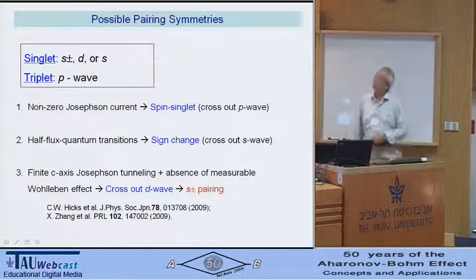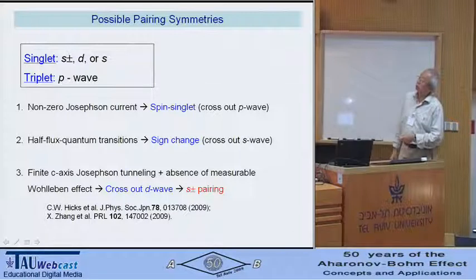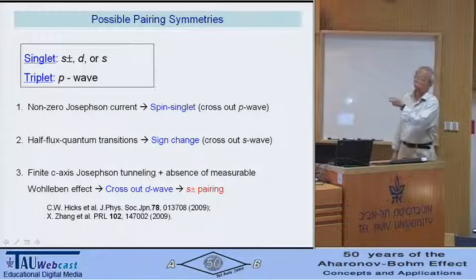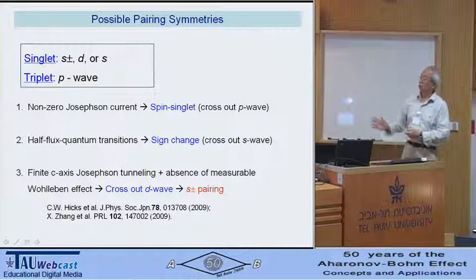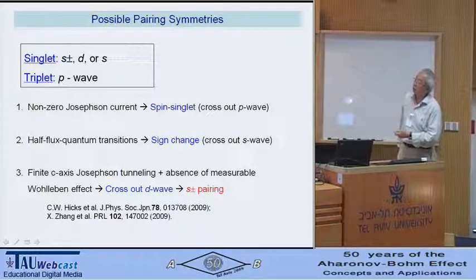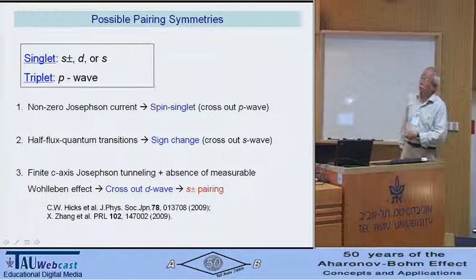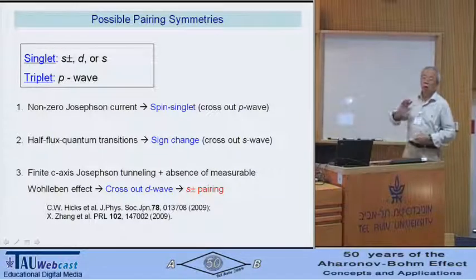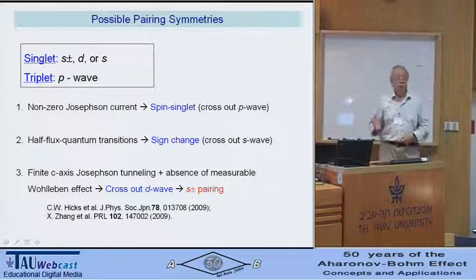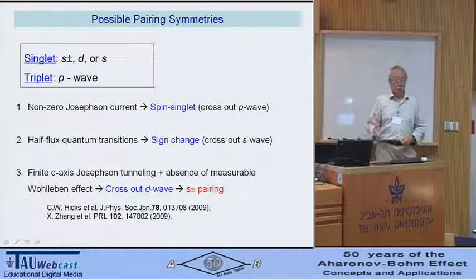Okay, now with this, we're in a position to say something. Since we see a non-zero finite Josephson current, we say it's a spin singlet. Half-flux quantum told us there's a sign change in the supercurrent flowing through the sample. And then we rely on other people's work published in the literature. I do not have it cited here. They clearly show it's not D-wave. So if you use that to rule out D-wave, then our experiment represents the first definitive experimental evidence to show the new superconductor is S plus minus.